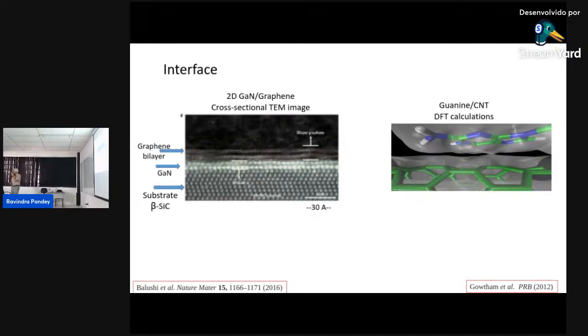So I'll focus on interfaces, and why they're important. If we look at the experimental part, we can image them. So this is a 2D gallium nitride with graphene heterostructure. If you look at the high resolution TEM image, you can see here this is a substrate, silicon carbide. You have a gallium nitride monolayer in this case, and then you have graphene coming out. So you can really count the number of atoms forming this interface. On the theoretical side, we have a really powerful tool based on the quantum mechanical model. We can look into the electron density of, say, graphene or a biological molecule with carbon in a tube, and how this electronic cloud density interacts. So both go hand in hand in terms of precision and the details about the problem.